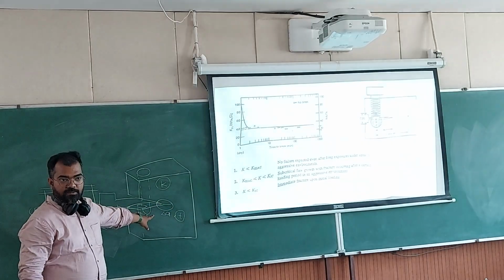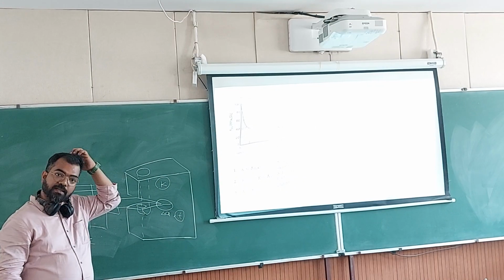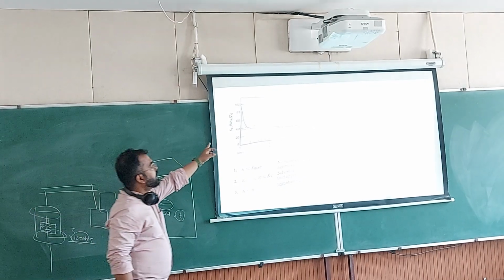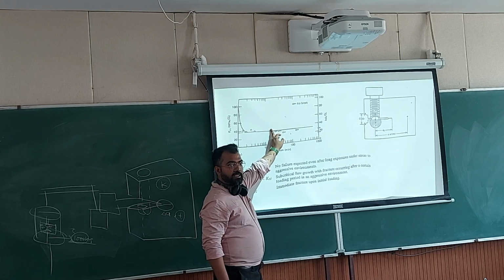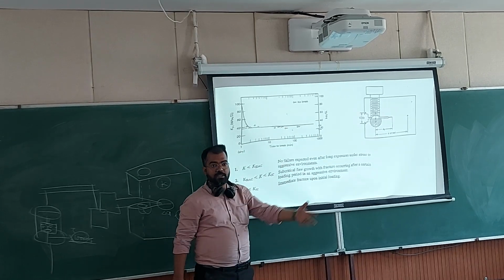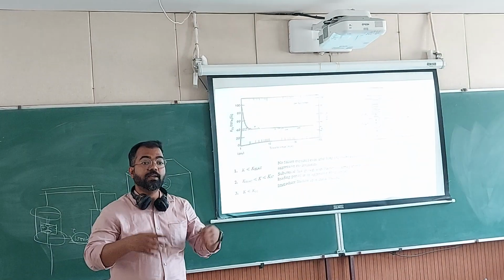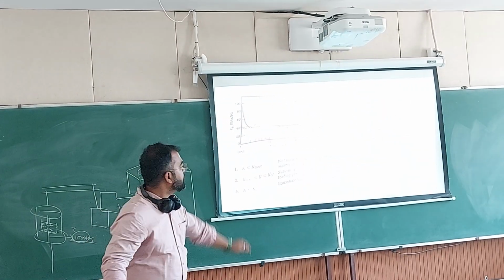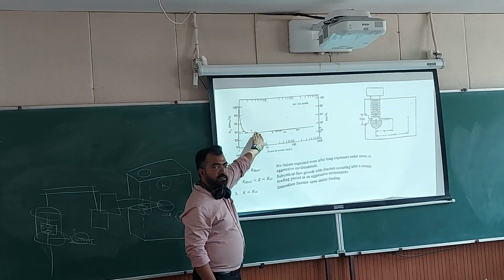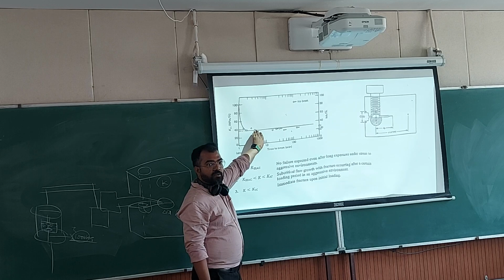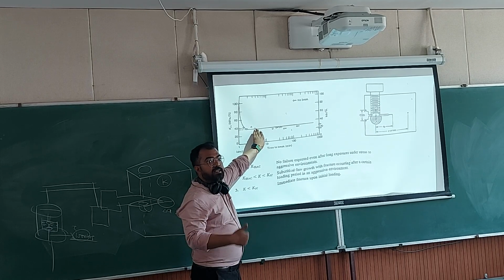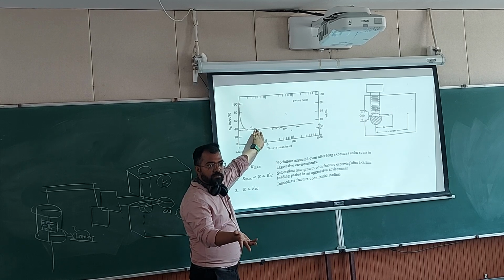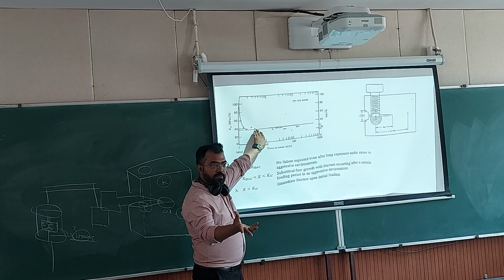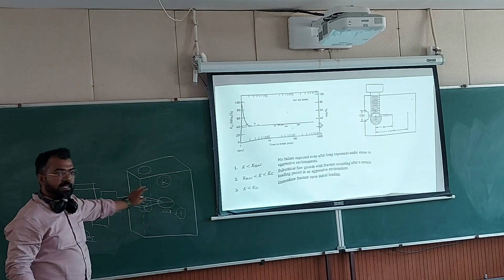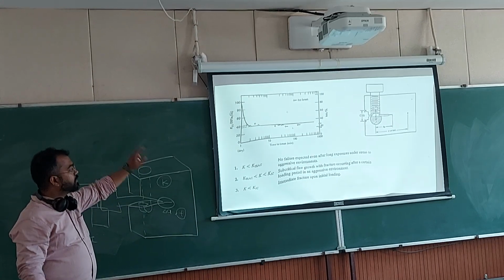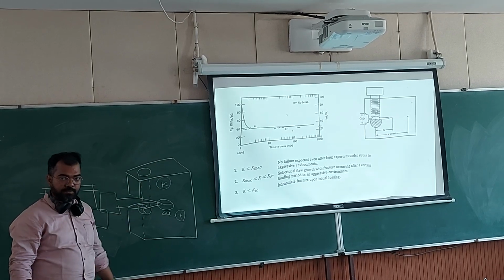The stress will not be 0 when you measure that no crack growth is happening. It will be some finite value of stress, and that stress will be giving you the value of KTH. It doesn't have to go to 0 for no crack growth to happen. It will not go to 0. Okay? Because once the stress reaches this stress intensity factor, crack is not going to grow anymore. If the crack is not growing, you will have no load drop. So the stress will never go to 0. Okay? So whatever COD you get here when the crack is not growing, that is your KTH, and this whole value of KTH you can generate from one sample.